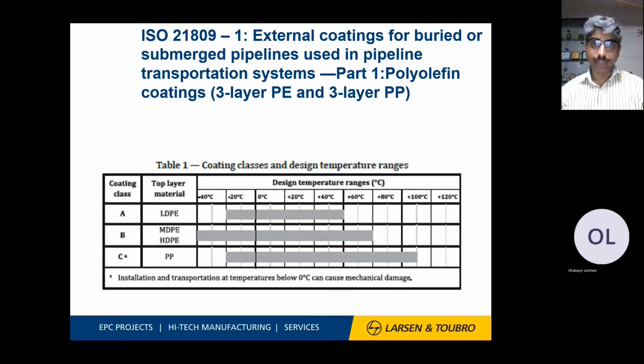How to go for the ISO 21809 requirement for external coating in terms of buried and submerged pipeline applications. There are three classes, A, B, C, based on the top layer material, that is LDPE, MDPE, HDPE, and PP. PE stands for polyethylene, PP stands for polypropylene. These are combinations of polyethylene and polypropylene material resistance based on the design temperature of the coating. So -20 to +50 or +60, this is the range. The second, B category, is slightly cooler or cryogenic, up to 80, and polypropylene can withstand very high temperatures, say up to 110 degrees centigrade. So it is possible for us to read the standard.